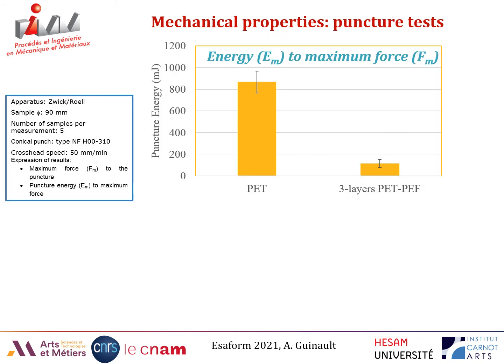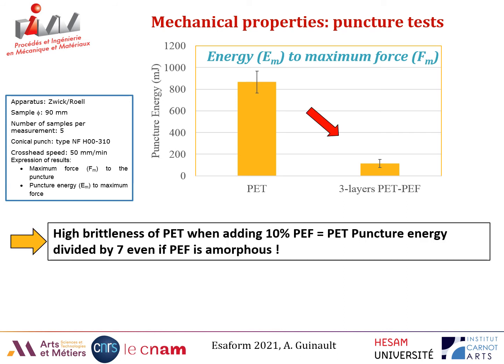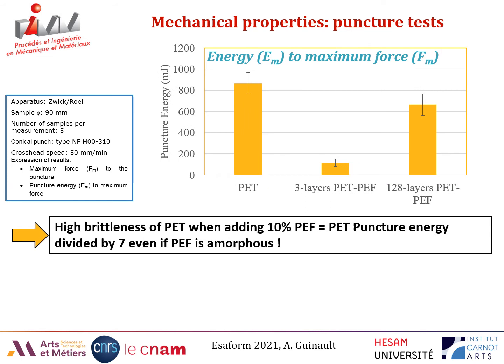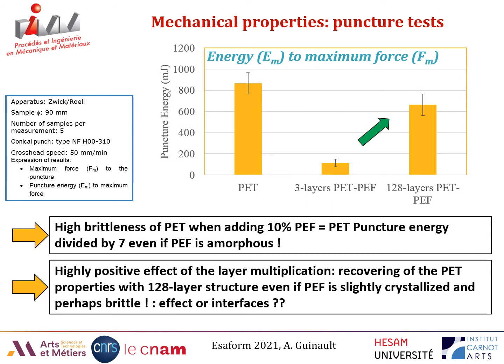About the mechanical properties in the puncture test, it's more interesting because in this case you can see that when you add PEF in PET 3-layer films, you can see a high decrease of the puncture energy that is divided by 7, even if finally PEF is amorphous. So it's a dramatic decrease for the PET. Now, if you do a film with 128 layers, you can see that you have recovered the value of the PET with the same proportion, finally, of PEF in the film. And so we have a good result, but perhaps as PEF is brittle, perhaps it is only an effect of interfaces.